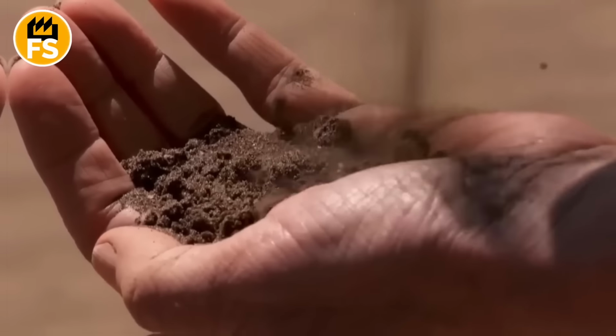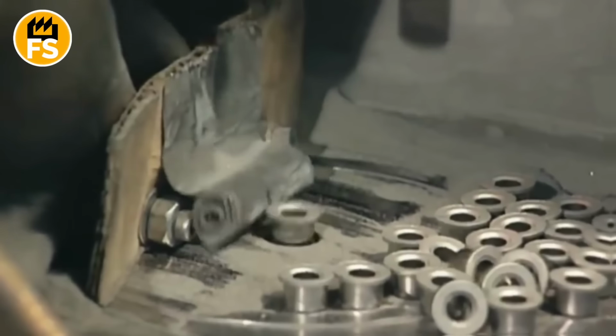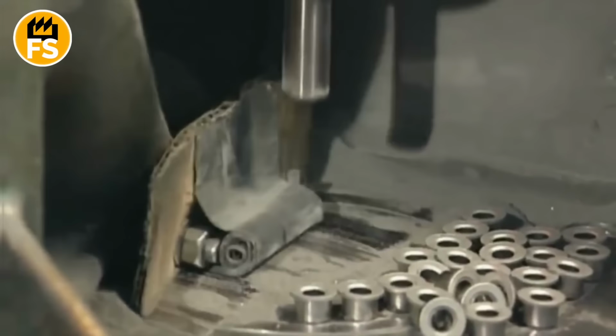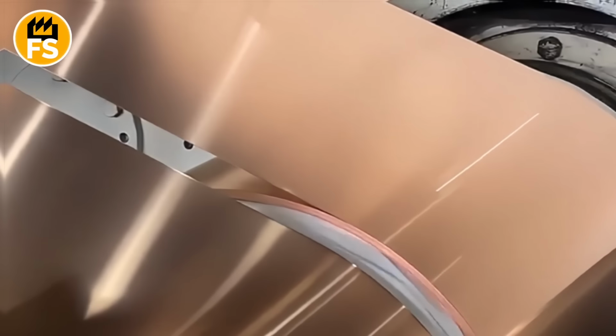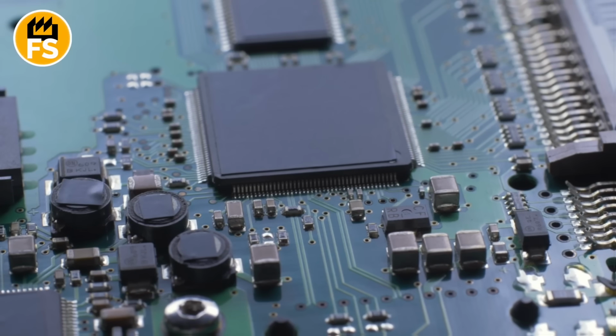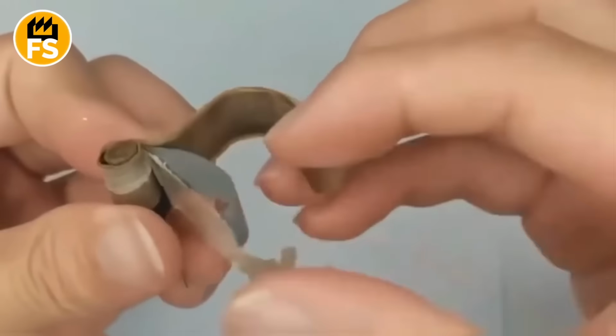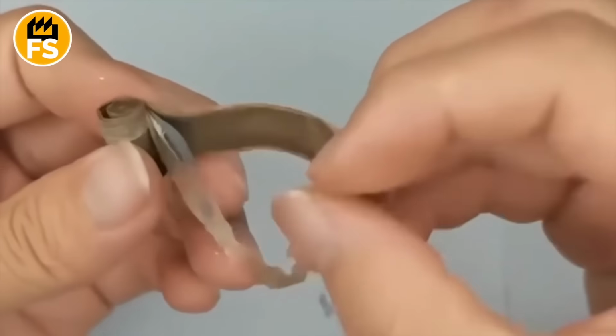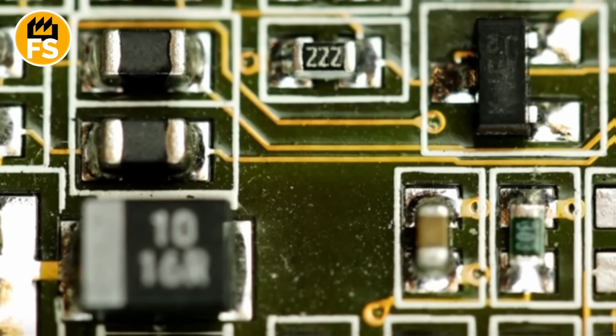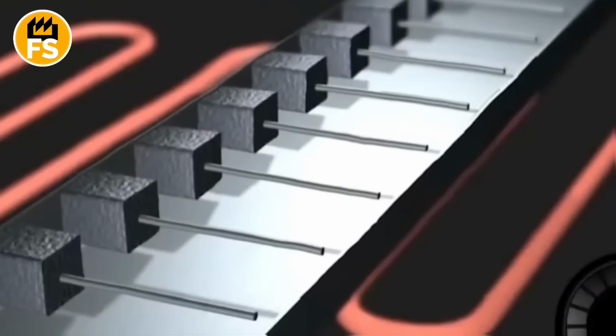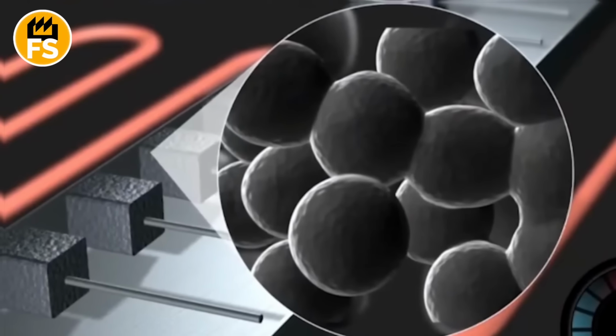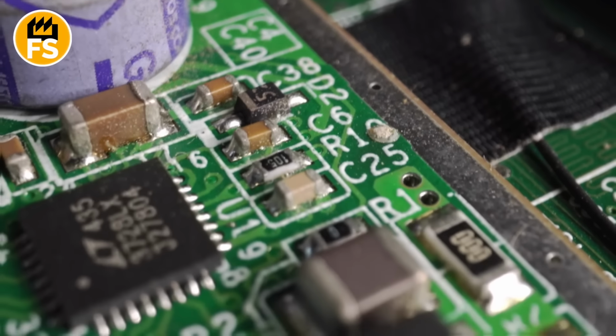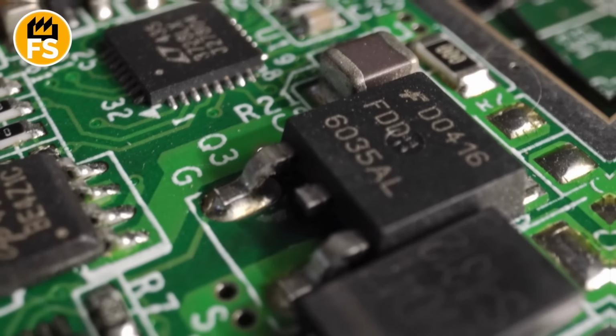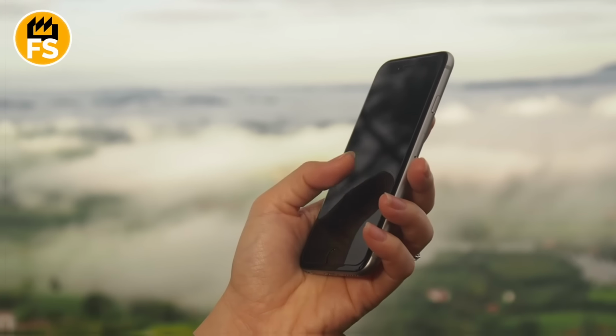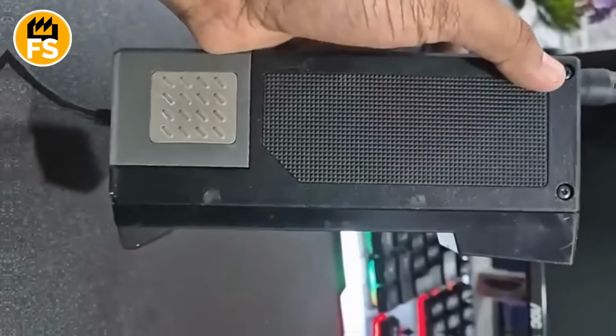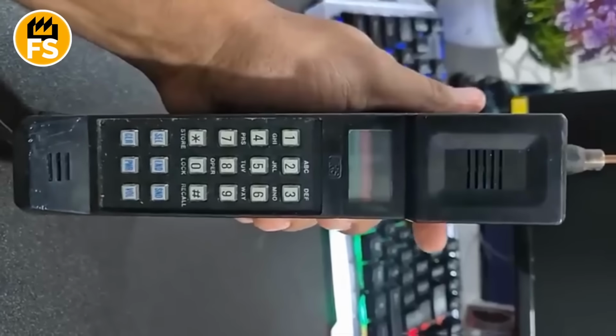Extracted tantalum is converted into powder, which is then pressed, sintered, and turned into anode foils for capacitors just a few micrometers thick. A tantalum capacitor works simply. Thin foil is coated with an even thinner film of tantalum oxide, which acts as the dielectric. Thanks to the microscopic thickness of this film and the massive surface area of the porous structure, you get enormous capacitance in a microscopic volume. This allows electronics to be compact. Without tantalum capacitors, smartphones would be the size of bricks.